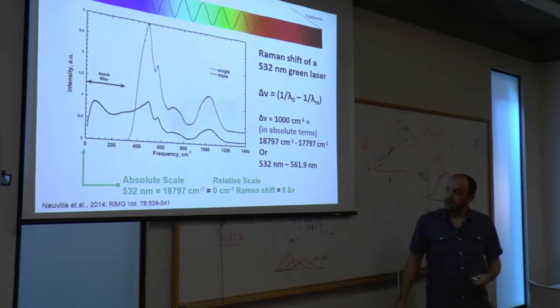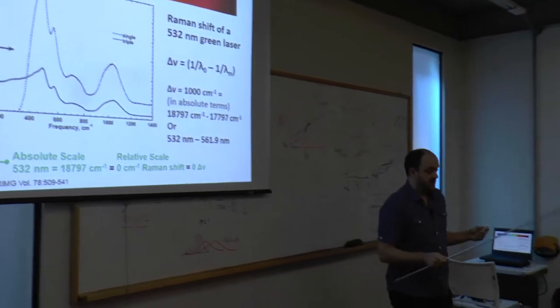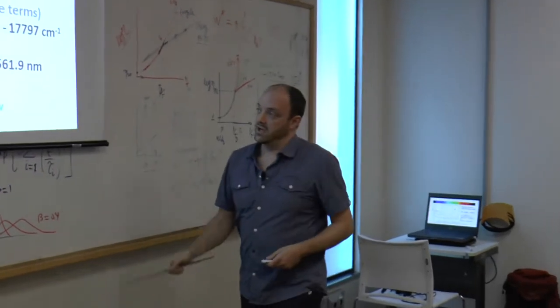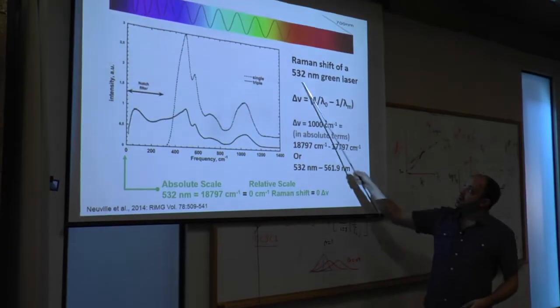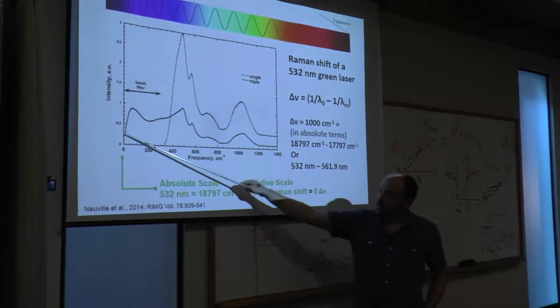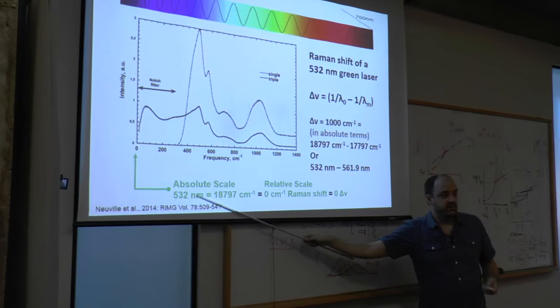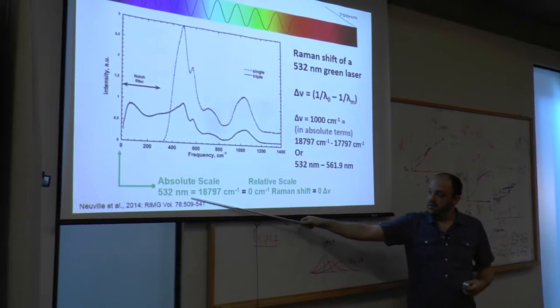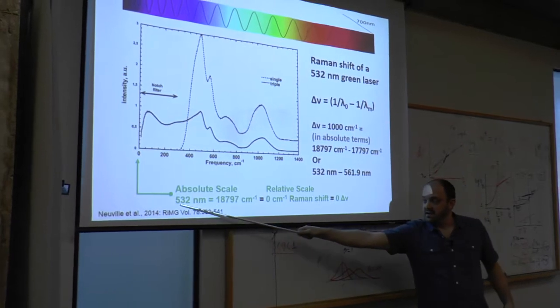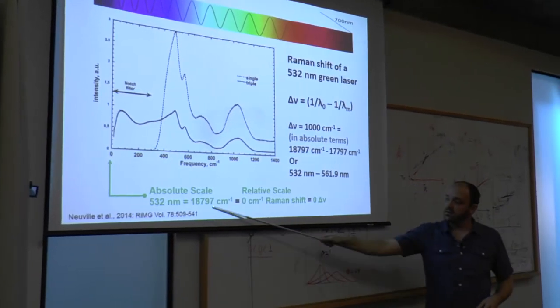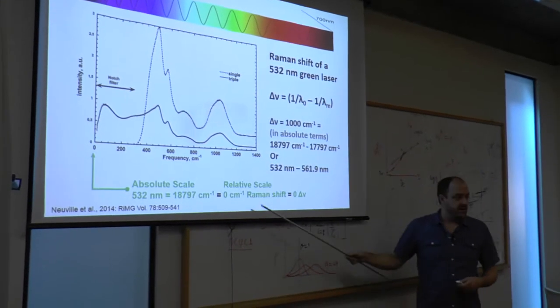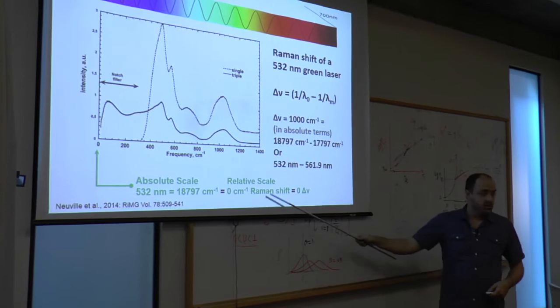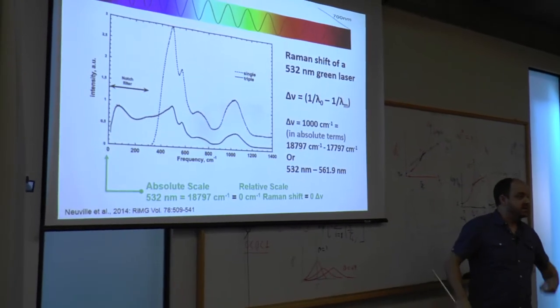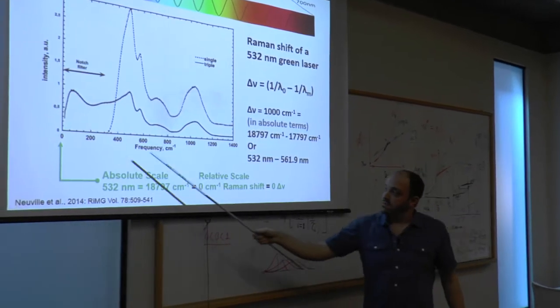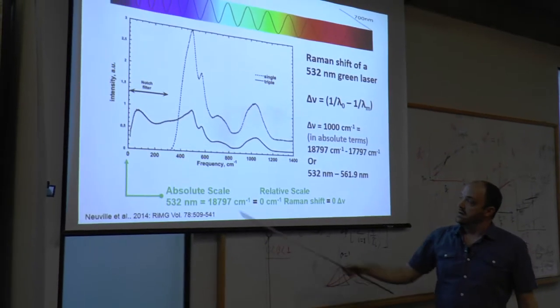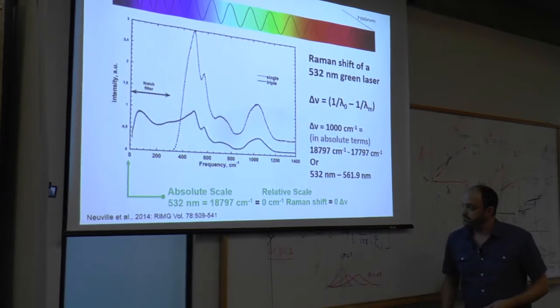When we look at a Raman spectra, we usually look at the shift in this frequency, right? The Raman shift or the change. But we always have to keep in mind what our initial wavelength is. So at 0 on any Raman spectra is the actual wavelength of light of the excitation of the laser that you're using. So in this example, 532, it's equal to this many inverse centimeters. And in the relative scale that we use in Raman spectra, it's actually 0 Raman shift, because this is the Rayleigh scattered light. It's the same as your excitation wavelength. As you move across, we have the Raman shift, light at different frequencies.